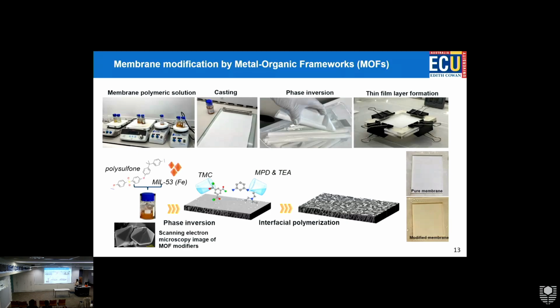So after this, we can test the membranes and see what the efficiency is. In terms of integration of different materials that I just presented, MOFs, COFs, zwitterions, etc., we mix them in the aqueous solution normally, and then they get integrated into the structure of that layer. Sometimes we also mix them in this polymer solution to increase the pore size and improve the properties of the ultrafiltration layer, and synergistically they have better properties.